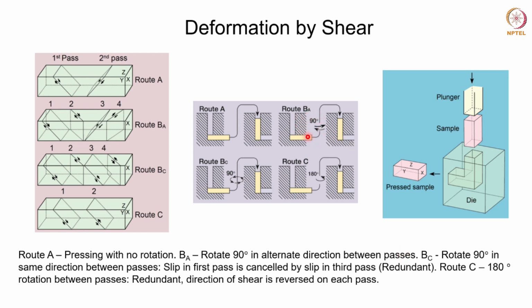That you can see here. This is the first pass, and then in the second pass it will be rotated 90 degrees in one particular direction, and in the next pass it will again be rotated 90 degrees but in the other direction. Then you have route BC, which involves a 90 degree rotation in the same direction between passes, as you can see from this diagram. And then you have route C, which involves 180 degree rotation between passes. That is again shown in this diagram with the help of an element. A small element is shown as to how it deforms as the workpiece is rotated between the passes.